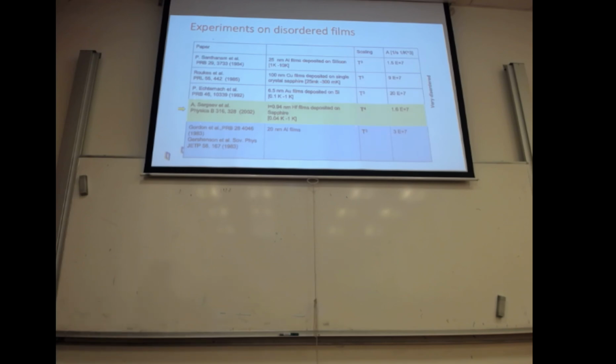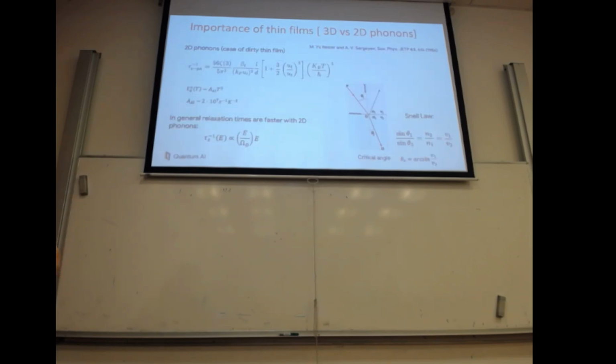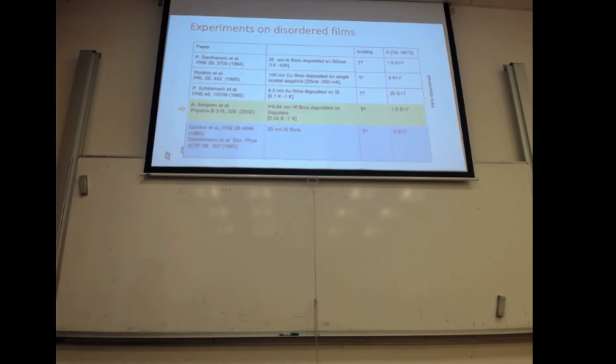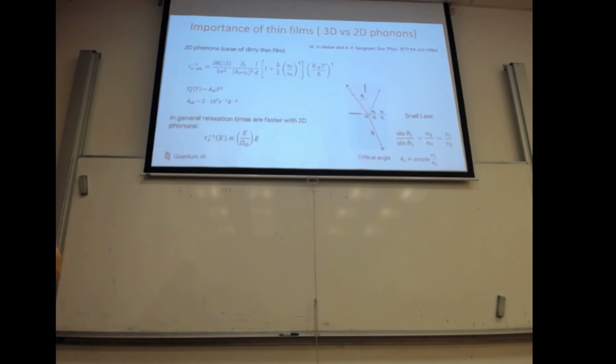So the first question that comes to mind is, it seems that this is something not yet solved. Why, for thin, disordered films, we don't have T4, but we have T cube? And why did Gershenson find T4? So I think that we could answer, and the answer was that Reiser himself said, okay, if the phonon in the dirty limit is 2D instead of 3D, then I expect to have a T cube dependence for the dirty film. But unfortunately, the value that he finds is not in agreement with what we find, and that is the first problem.